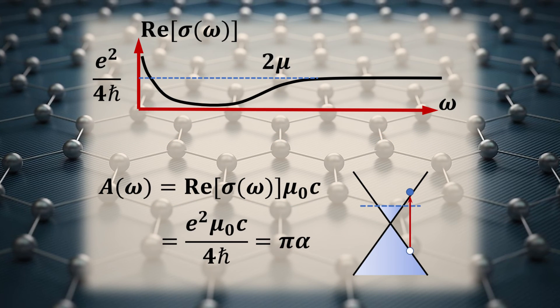In summary, the universal optical absorption of light in graphene is defined by the fine structure constant, or more precisely, pi multiplied by alpha. This leads to an optical absorption of about 2.3% for suspended graphene. The fine structure constant is traditionally associated with quantum electrodynamics, rather than in material science. Thus it is surprising that simple light scattering experiments with graphene can reveal this fundamental constant.